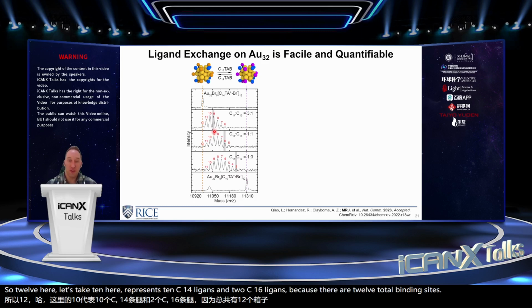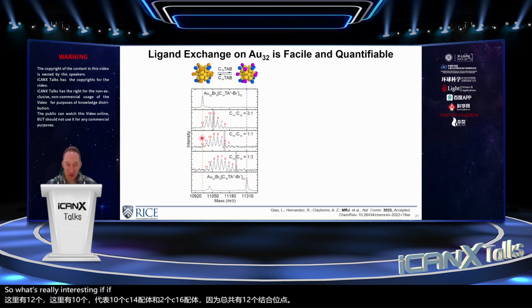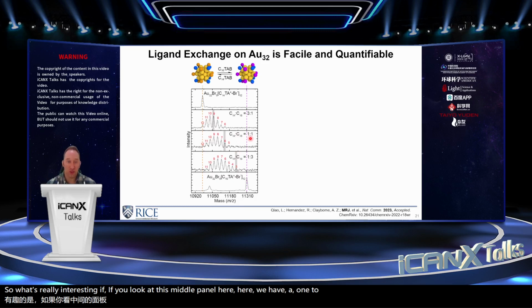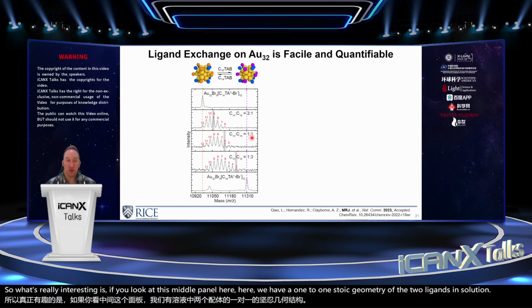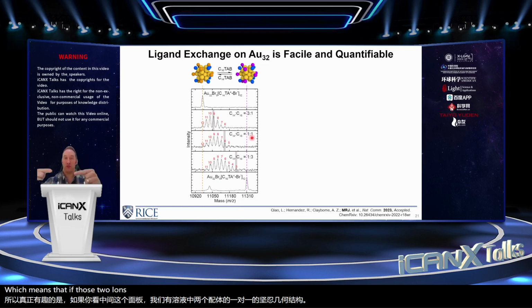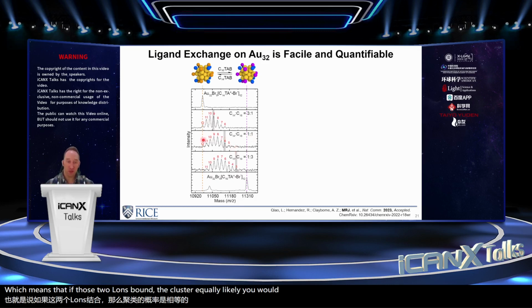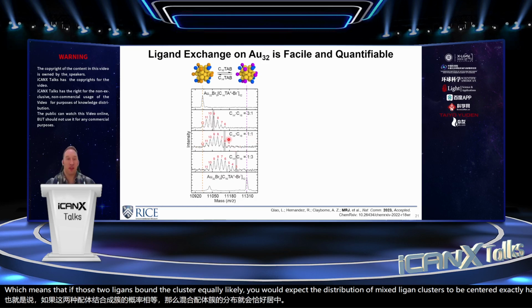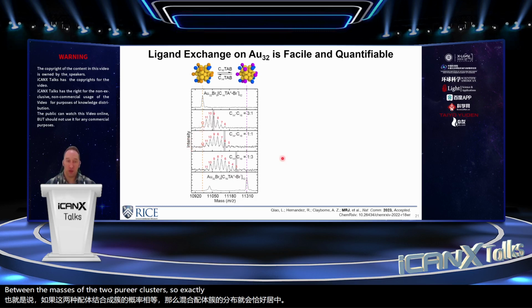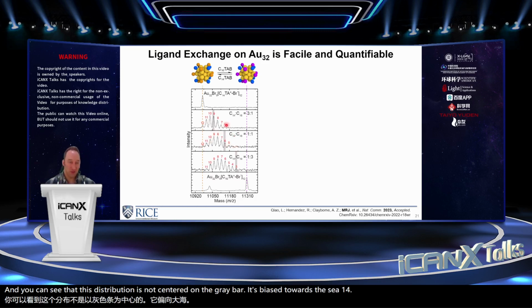binding sites. So what's really interesting is if you look at this middle panel here we have a 1-to-1 stoichiometry of the 2 ligands in solution, which means that if those 2 ligands bound the cluster equally likely, you would expect the distribution of mixed ligand clusters to be centered exactly halfway between the masses of the 2 pure clusters. So exactly halfway between this mass and this mass, i.e. where the gray bar is. And you can see that this distribution is not centered on the gray bar. It's biased towards the C14 ligand. So that tells us that the cluster prefers to absorb C14 over C16 ligands when given equal opportunity.